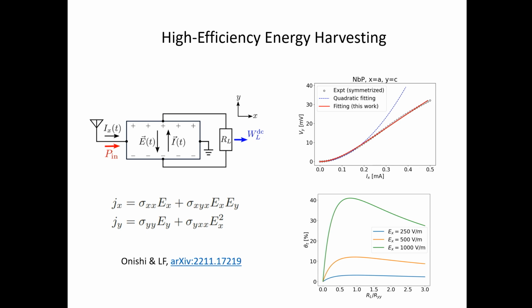So recently with my student, Yugo Onishi, we did a simple calculation and estimated the power transmission efficiency, and that generally depends on the matching between the internal resistance of the material and the external load. But under the optimum condition, the power conversion efficiency can reach something like 40%.